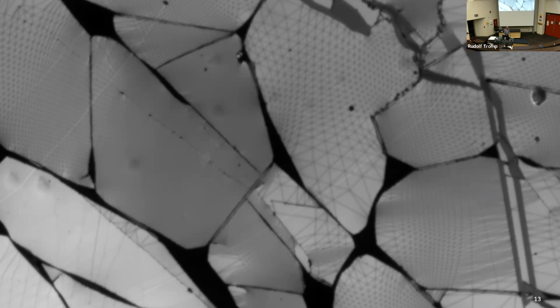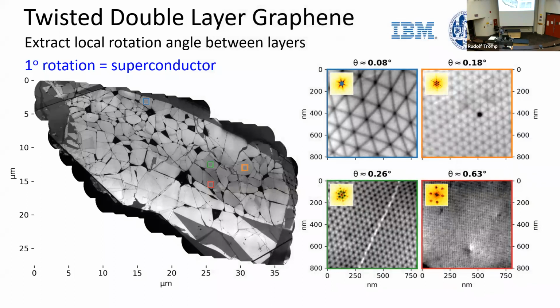So people are interested, and people call this twistronics now. You're going to call it something tronics, so it's called twistronics. It's how the electronic behavior of these materials depends on twist. So now we can look at a few different areas and get images. And so here we see images at 0.08 degrees rotation, 0.18, 0.26, and 0.63. And you see those dark lines in the image, which are part of the characteristics of this moire pattern, right? And they allow you to, just from the Fourier transform, calculate the twist angle.